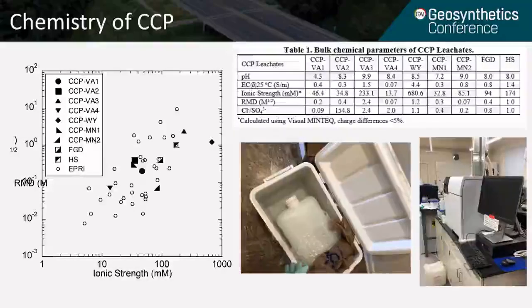In this study, the closed symbols are samples from this study, and the open symbols are a database from the EPRI report that Dr. Benson and I worked on in 2015. So we can see the chemistry of recent years hasn't changed too much. The agreement is good, except one of the leachates is higher than the whole, which is nearly 700 millimolar.